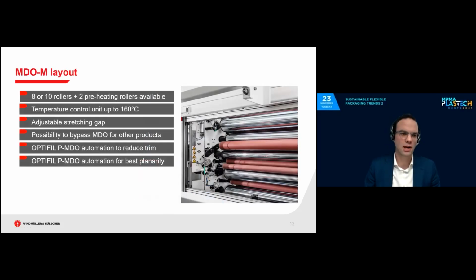So our MDO-M, as we call it, is very modular and tailor-made to your needs in the end. It can be 8 rollers, 10 rollers, plus 2 additional preheating rollers are available. So in the end, we look up to 12 rollers. Each roller is temperature controlled up to 160 degrees to make sure that also high density material can be nicely heated up and stretched. The stretching gap itself is adjustable to your needs, to the product needs.